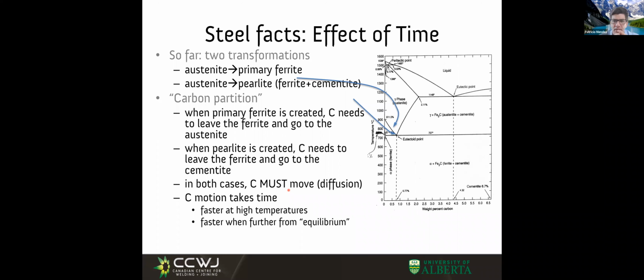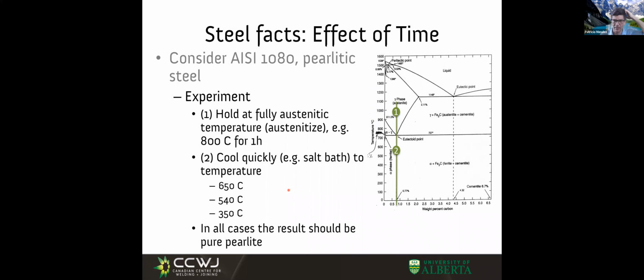Fast, of course, right? So now you start seeing, and we are only starting the conversation, but you start seeing a coarse microstructure takes long, fine microstructure takes short, but transformations at high temperature can happen fast, and transformations at low temperatures happen slowly. We start to put together some very important concepts that explain hydrogen cracking, and explain why we can mess up a weld with the wrong heat input. So if you bear with me, we go little by little.